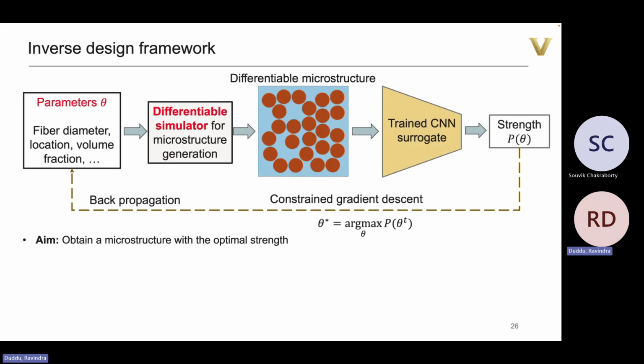Okay, so what I did was you have the design parameters, but in our case, the fiber diameter is fixed. The location is varying. The volume fraction is also fixed, right? So we are not considering all the design parameters. The only design parameter we're allowing to change is the location. That means moving these fibers randomly. So the question we asked is, is there an optimal pattern of these fibers that gives the maximum peak load? Very simple question, simple microstructure, toy problem.